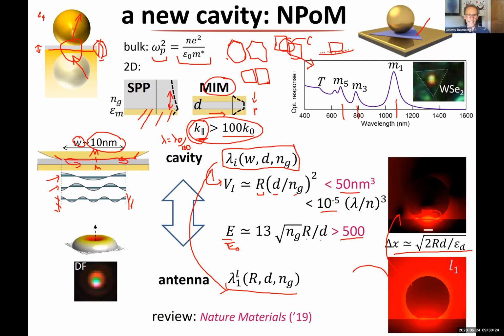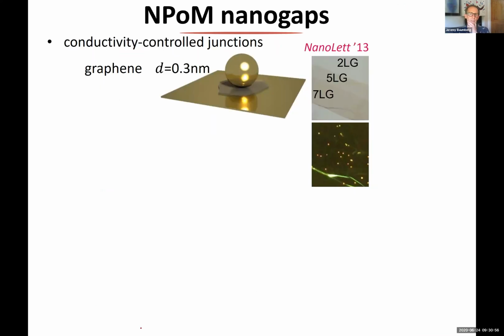The other interesting thing to see is that for these antenna modes, because the field of the cavity mode here is vertical, because it has to be across the faces there, so the optical field is always vertical, then this can only radiate out to high angles. So the tightest confined modes in these gaps always radiate to high angles. And if you look at them in optical spectroscopy, you see this ring. And that's a clear sign that you're looking at a Z polarized dipole. So that gives you a good feeling. That's basically the theory I wanted to show. That gives you a good feeling of why the light is very tightly confined.